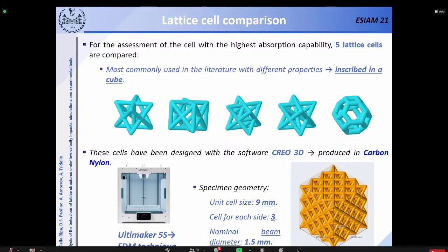I can comment about this. I don't know if it was a macro scale specimen or not, but I believe yes. And indeed, you can think about a size effect between lattice structures and the specimen under test. My feeling, according to the results that we got, is that even this effect was hindered by some other aspect, and in the finite element model, the agreement was quite good. Okay, and the last question.